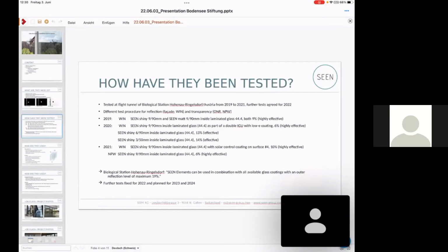In 2020, we repeated the test with the SEEN Shiny 9/90 pattern, but this time we used the laminated glass, which we tested the year before, as part of a double IGU, because this is usually the application we have on a facade. And the IGU was made with a low-E coating. And we got an even better result with only 6% of the birds flying towards the test glass. So we were again highly effective.